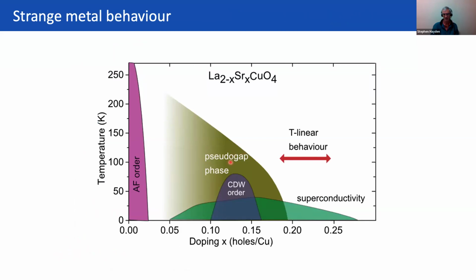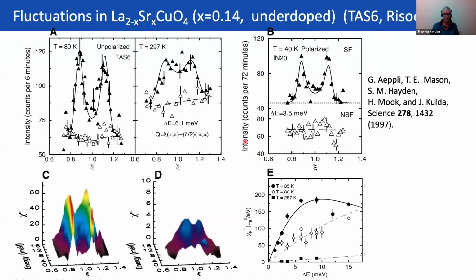And just to put things in context, I'll show you some older data which we took a long time ago, when I was working with Gabe Aeppli and others, and this is actually a sample here in the underdoped region. So in the underdoped region here, we found incommensurate peaks, and here you see different temperatures, what the response looks like, and you can see it's strongly temperature dependent. This one here is at about 300K, and then this one here is at about 35K. So this one's actually about TC.